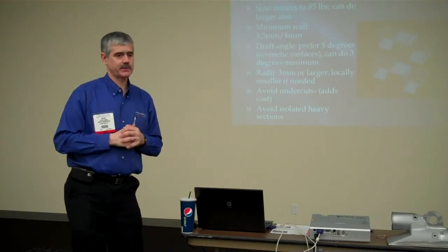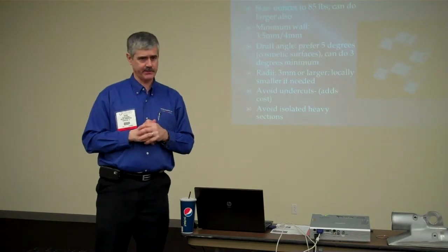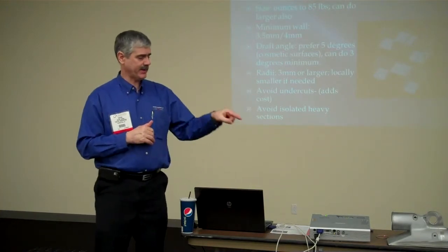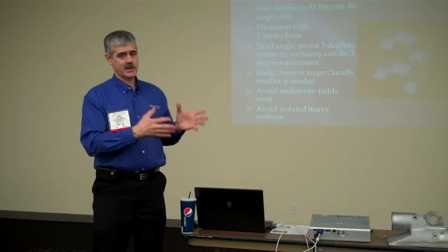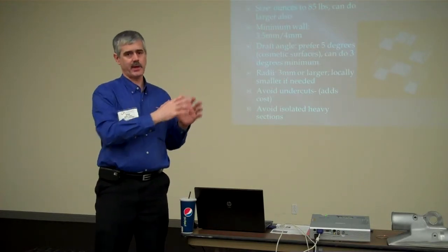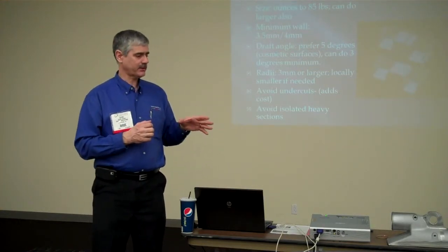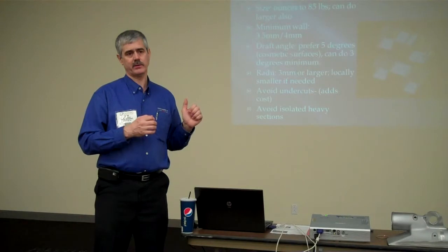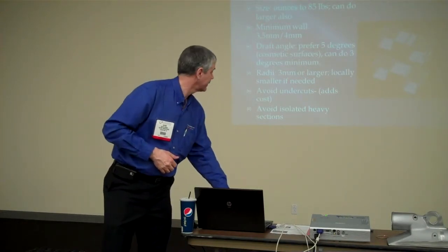Isolated heavy sections. That's something that's very important if we're going to be looking at holding a part pressure tight. And on this part, I've got some slides of the magma coming up, and you'll see what we did. We did analysis on it. It had heavy sections that were in the middle of the part, and we can't get feed metal into those. So the problem was solved by reducing the mass of the part and sort of hollowing it out. I think that's coming up shortly here.